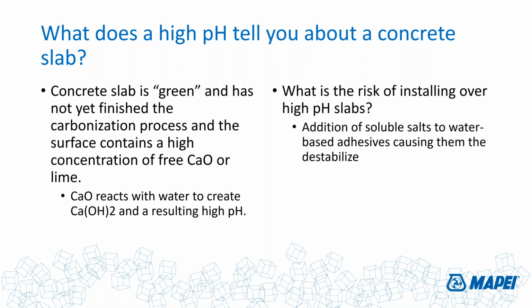And what that means is that the surface has a high concentration of calcium oxide or calcium hydroxide, and so on. The calcium hydroxide is a very important component of cement. When cement reacts with water, it creates that calcium hydroxide, that's the lime portion, and that will result in a very high pH.